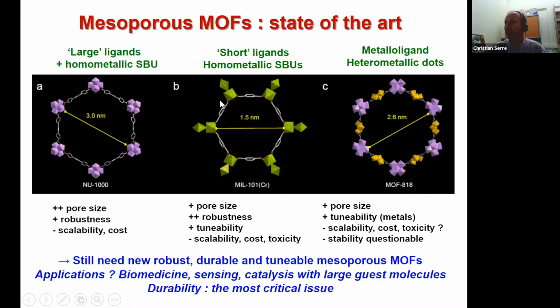Another strategy that was reported before is to use a small building unit still, but then a normal, I would say, simple aromatic carboxylate ligand. And in this case, they form some association like hybrid supertetrahedra, like zeolite tetrahedra, but instead of having silicon ions, you've got an oxo cluster. And therefore, they associate like a zeolite and they form zeotype architecture. And in this case, despite the fact that you use small ligands, you can have mesopores. Of course, this is advantageous in terms of stability because these short ligands are less prone to bend themselves when you remove the solvent and therefore collapse.